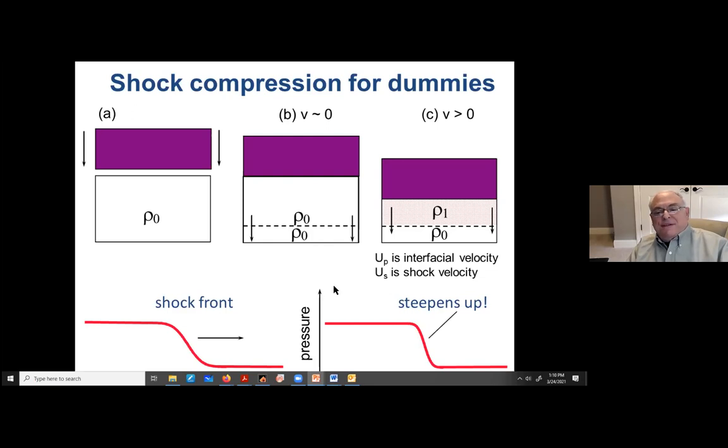Now, I want to tell you my favorite feature of shock waves, which is, I mentioned here that an acoustic pulse will disperse. But a shock front is a nonlinear excitation, and it steepens up. Here's one way of thinking about it. This could represent, let's say, pressure or density versus position. And this is in front of the shock front, nothing's happening. And then here's the rise time of the shock front.